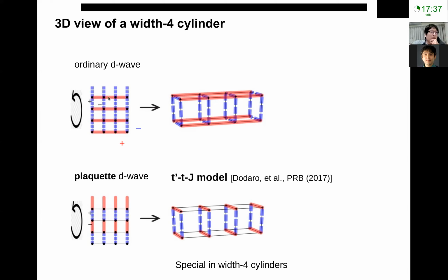And the ordinary D-wave in this 3D view would be like the D-wave superconductivity on the surface, like wrapping on the surface. However, the other pairing symmetry we found in this 3D view is more like a D-wave on the plaquette.